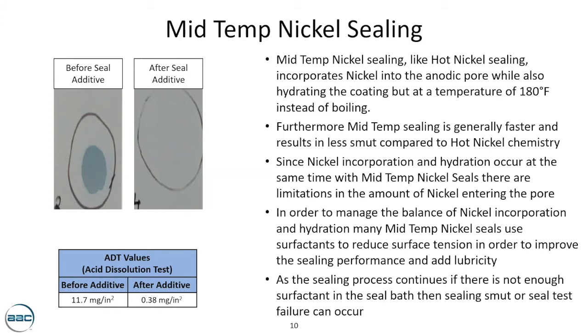So what you'll see here again is a phenomenon wherein there wasn't enough of that seal additive or that surfactant. The part failed blue dye stain. An addition was made of that surfactant, and now you've passed blue dye stain. And the critical thing here is a lot of customers will dump their baths the minute they fail a blue dye stain, wherein it could be something as simple as just making an additive addition. So keep that in mind when you're assessing your sealing chemistry.